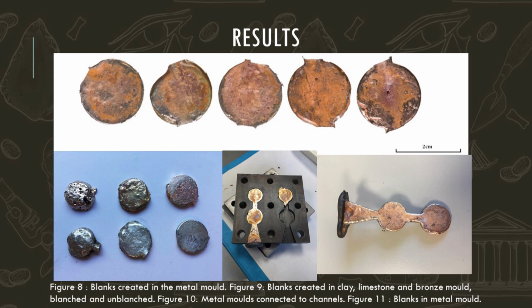To facilitate the mass production of coinage, moulds must be able to produce large quantities of flans in a single casting, and the introduction of the molten metal into multiple channels would increase the probability of mould failure. Modern potter's clay is similar compositionally to the clay used for ancient refractory items. These experiments suggested that the clay moulds would be used only once and new moulds would be required for each casting. And when you consider the mass production of blanks, this would significantly increase production times. So for this reason, it appears that clay moulds would be an impractical choice when considering the other materials available.